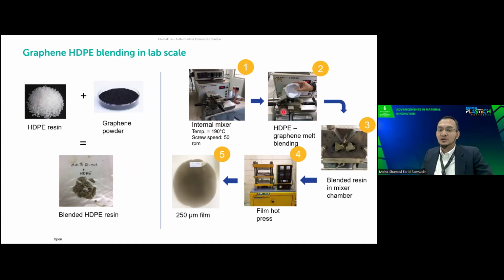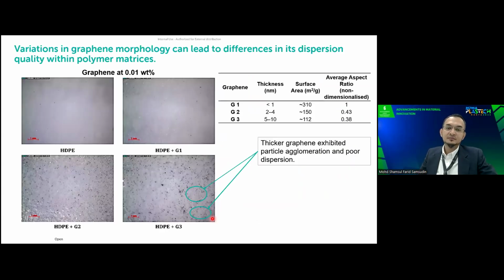We control a certain temperature, for this case around 190 to 200 degrees Celsius, at a screw speed of 50 RPM. And even though this compound, in terms of the volume, is very small, around 50 grams, in terms of the mixing we can see there is an improvement in the dispersion of graphene using this melt blending technique. So from here, we make it into a thin film for different types of testing and characterization.